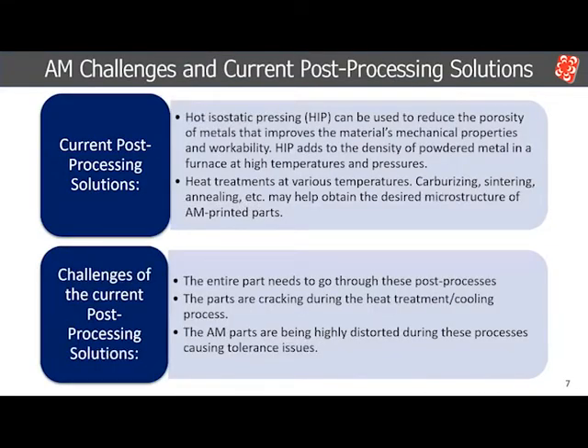To combat that and to enhance the fatigue life, a lot of post-processing techniques are being used after the additive manufacturing process. The most common ones are the HIP process and heat treatments, and these come with their own challenges. In addition, there's a lot of work around post-processing techniques used to reduce surface roughness, like machining, milling, and chemical reactions, with the goal of reducing surface roughness to enhance fatigue life.